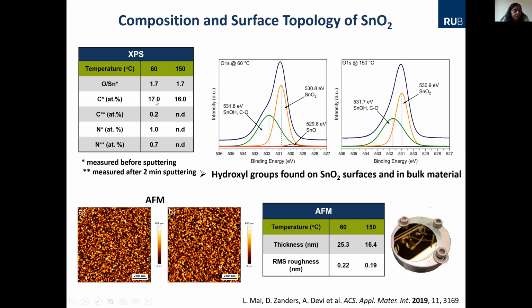You can see the carbon is very low on the outer surface. Before sputtering, you see around 17 atomic percent, but after sputtering, that means you remove the first couple of layers, it comes to less than 0.2 atomic percent, which shows that the film is actually very pure. And the oxygen deficiency, as I said, is one of the advantages for sensing applications. At low temperature you also have the monoxide. This is a dioxide, and you have the monoxide, but at high temperature this monoxide species disappears. So the spectra is deconvoluted, and you have the different species here. In that case, you can assign the OH species and the SnO2 phase here. But here you have a small contribution from the monoxide.